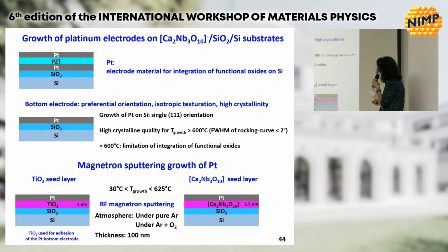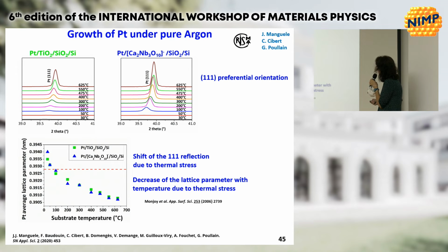Different temperatures, of course, have been looked at, and so we have worked with two atmospheres: one under pure argon and the second one, which is a mixture of argon and oxygen. So here is the result for the growth under pure argon. First, you can see that in both cases we have the 111 orientation, and we have a shift of the peak indicating a shift of the lattice parameter, which is due to thermal stress differences between the substrate and the films. And as you can see, on both samples you have exactly the same behavior.